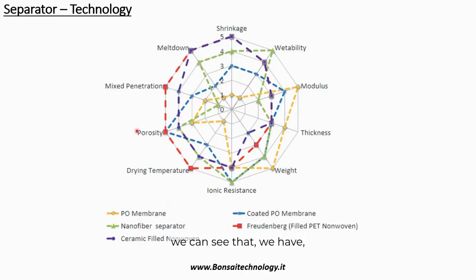lines, we can see that we have high porosity for the polyolefin membrane coated by ceramic coating. The reason why is the separator makers can allow bigger pore size without losing in safety, because there is their ceramic coating that increases the electrical insulation. Indeed, as mentioned before, this doesn't change the ionic resistance. I mean, it increases the ionic resistance a little bit due to the ceramic coating layer, but not a lot, and more or less they have the same properties.